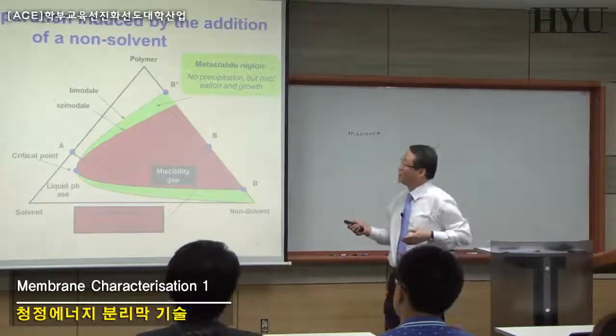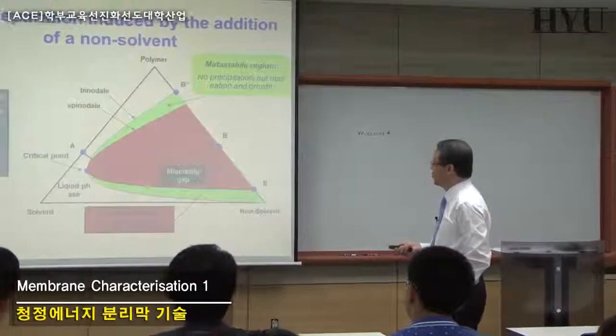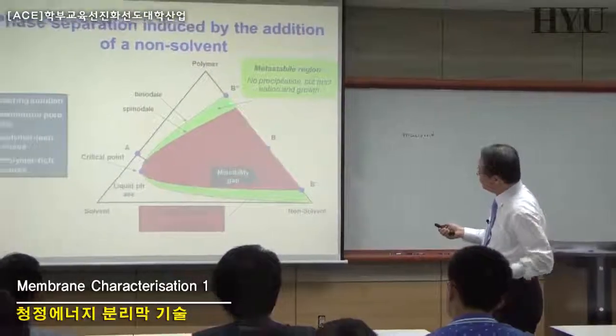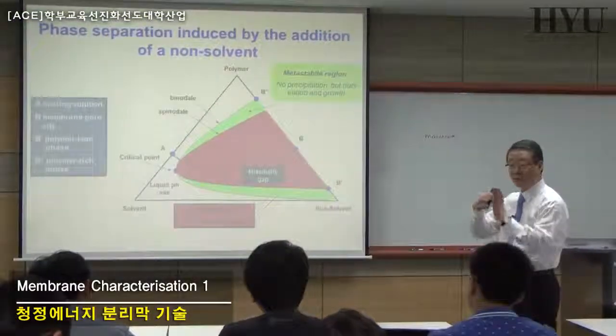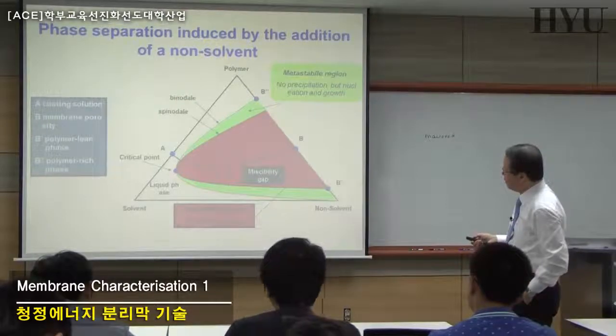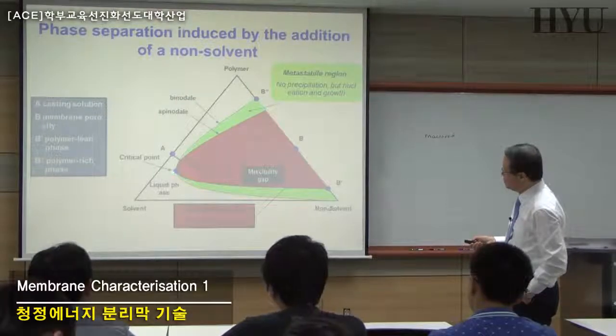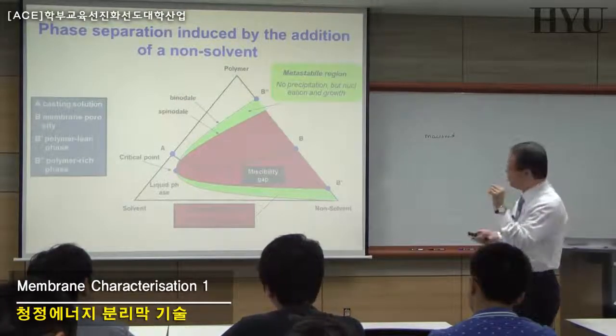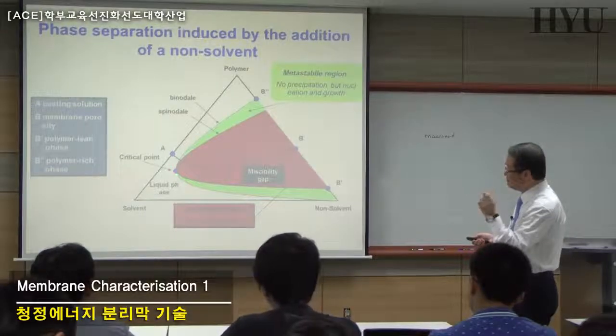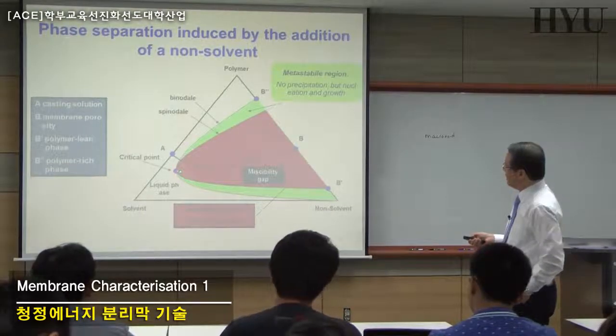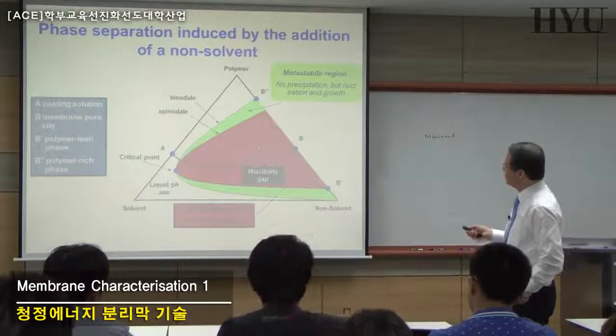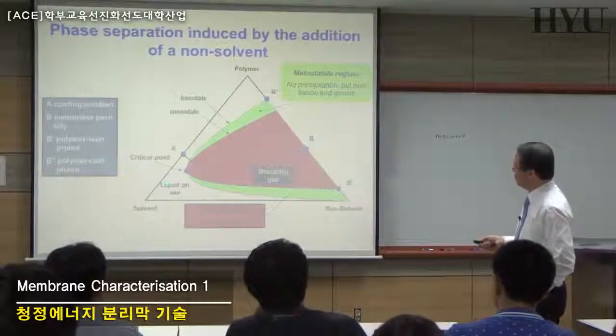In the case of the NIPS process, we have a polymer, solvent, and non-solvent. It looks very similar to what we have seen in our TIPS process. We have a critical point here, which is the top of those, where the binodal and spinodal meet together, and you have an unstable region, metastable region, and stable regions.